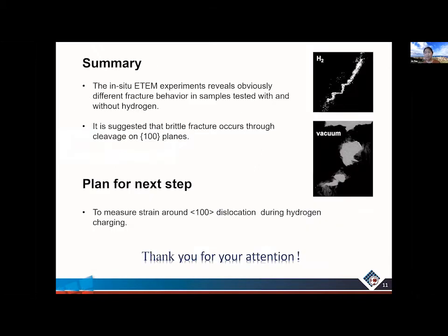To summarize what we have done in our TEM experiment, we have seen clearly different fracture behavior in samples tested with hydrogen gas and without hydrogen gas. And it is suggested that the hydrogen embrittlement occurs through brittle cleavage fracture on the 100 planes. So our plan for the future is to measure the strain around a 100 dislocation and to see how it will evolve with hydrogen charging. So that's all from my part, from my results, and I would like to have further discussion with you. So thank you very much for your attention.